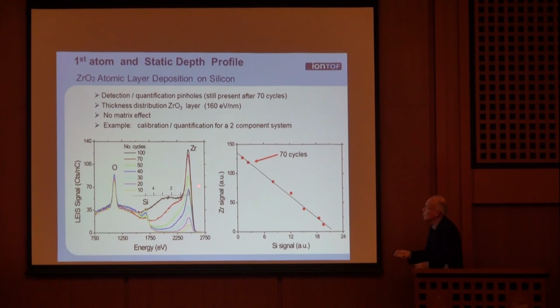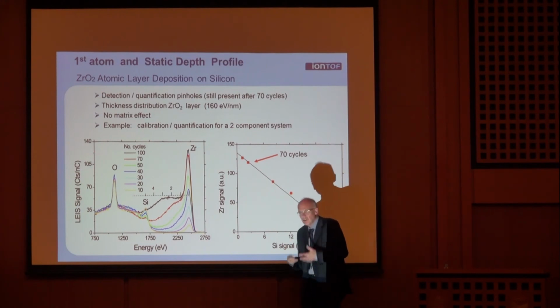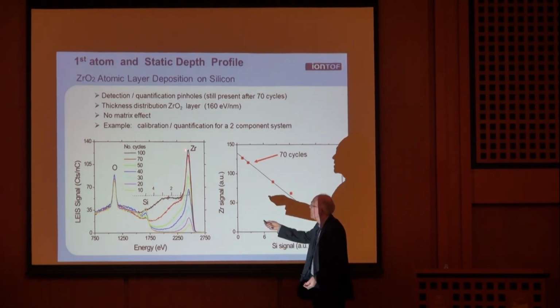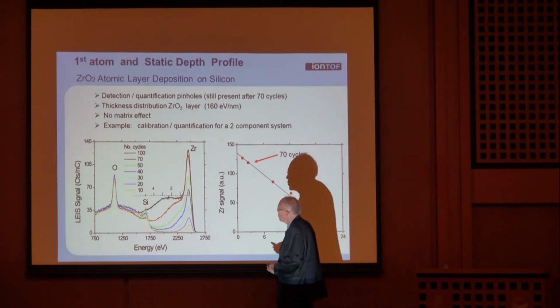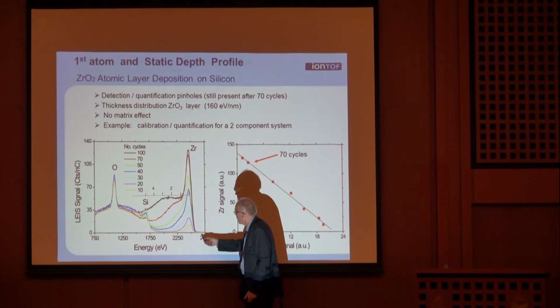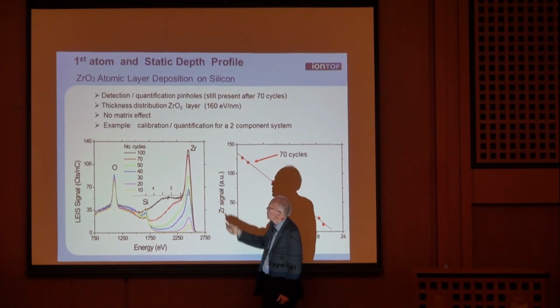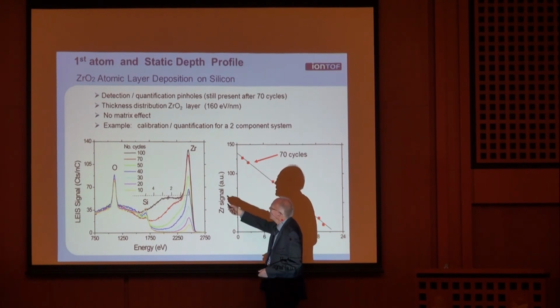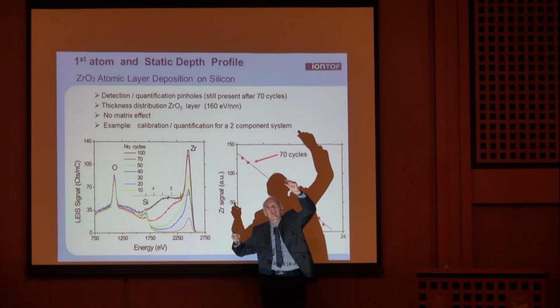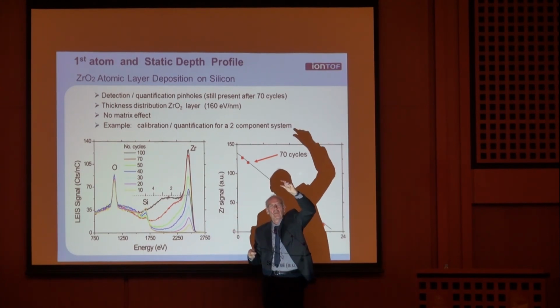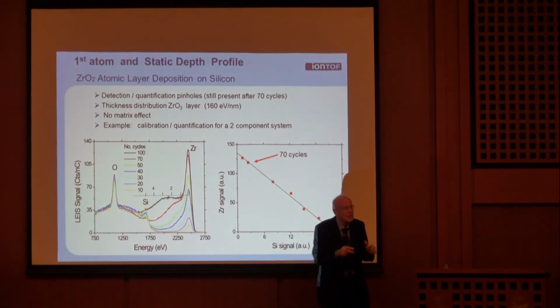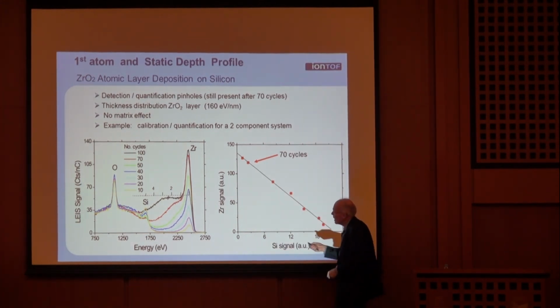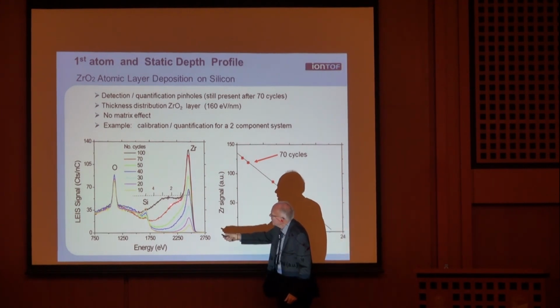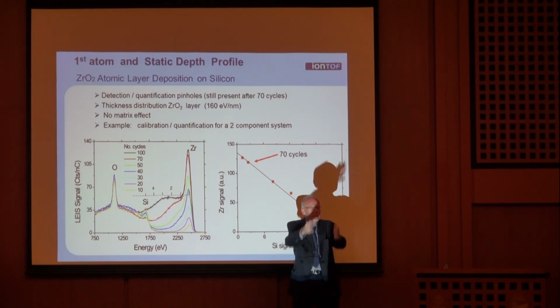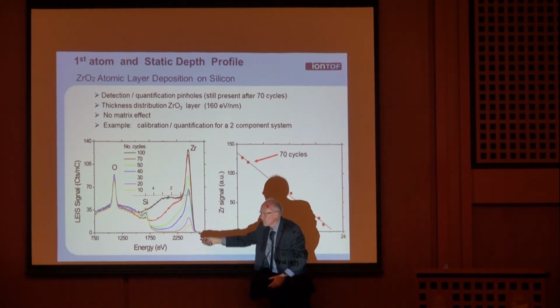I'll do this quickly. I started off with the example of zirconia on silicon. In general, when you grow things like this zirconia on a silicon wafer, when you grow more and more, the coverage goes up, so you get more and more zirconium. But you will see that even in the red one, there's still something missing. And this is an accurate technique. So if you miss that, you say there are still pinholes in the layer. It's not a complete coverage yet. However, you will see already for red that there is an asymmetry. Normally these peaks are Gaussian. Here you see there's a tail.